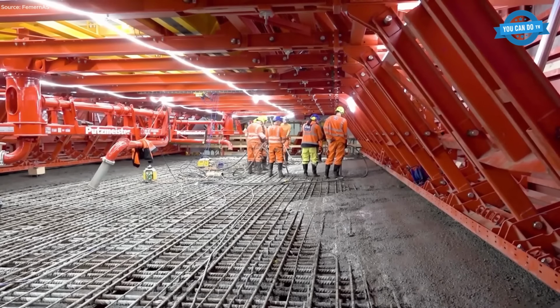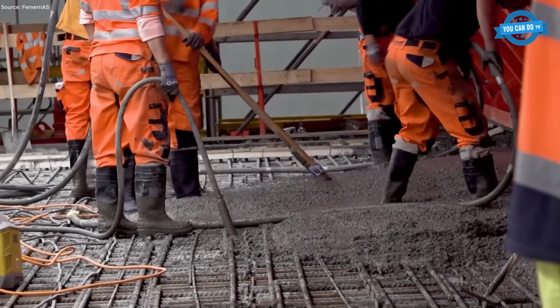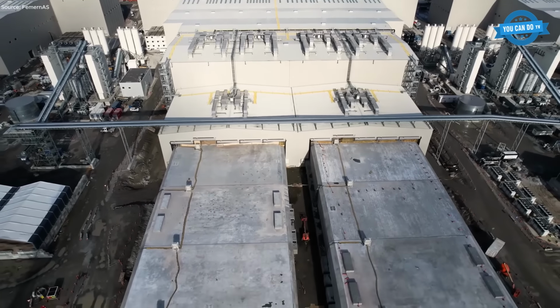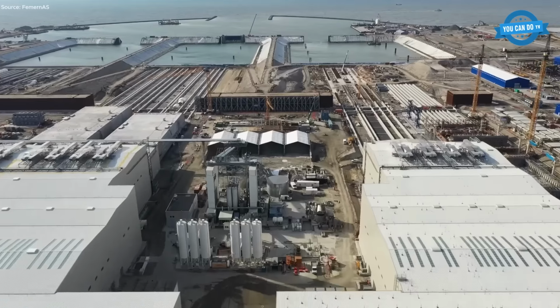Approximately 300 cubic meters of concrete are poured per segment, with casting lasting around 30 hours. Once cured, each 24-meter segment is advanced toward the dry dock. 9 segments are post-tensioned together to create a complete tunnel element.